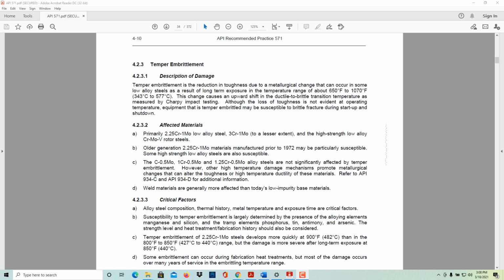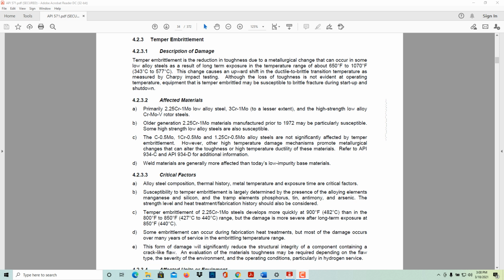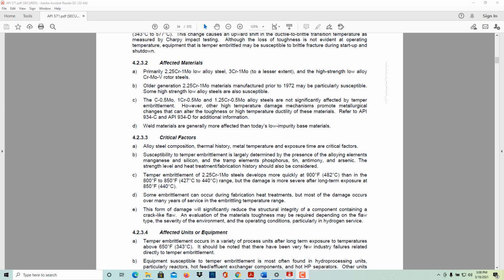Although the loss of toughness is not evident at operating temperatures, equipment that is temper embrittled may be susceptible to brittle fracture during startup and shutdown. Affected materials: primarily 2.25 chrome 1 moly and 3 chrome 1 moly low alloy steels, the latter to a lesser extent, and the high strength low alloy chrome moly vanadium rotor steels.